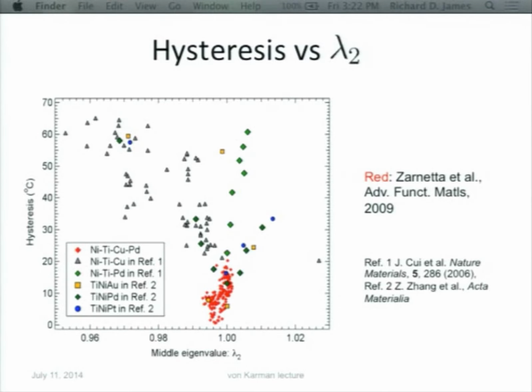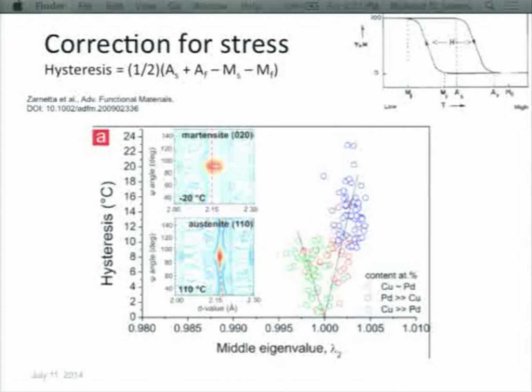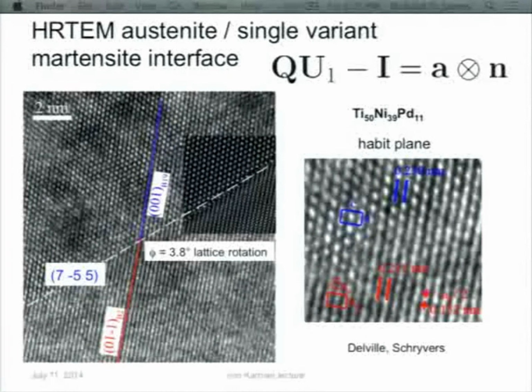The hysteresis was going down to near, this is the hysteresis, each dot is a different alloy, and this is the value 1. You can see it's, in fact, displaced a little bit from 1. That was understood because these measurements were done on films, and there was some stress in the films, and this was corrected for by the people who did those measurements. But you can see there's some alloys which have around 1 degree hysteresis, which at slightly different compositions would have quite large hysteresis.